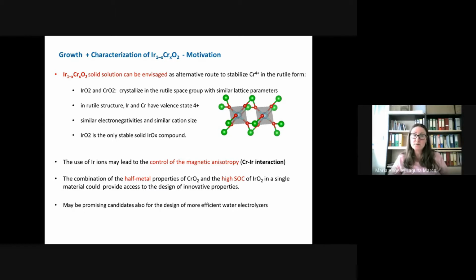The formation of stable iridium and chromium oxides with rutile structure hasn't been reported yet. However, it can be expected based on the fact that iridium and chromium conform the so-called Hume-Rothery rules for the formation of substitutional solid solution phases.